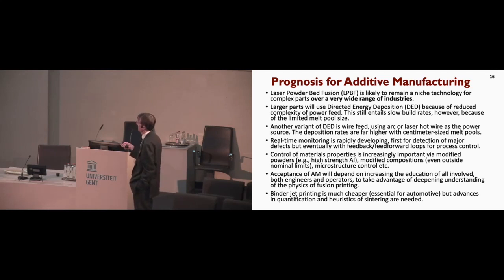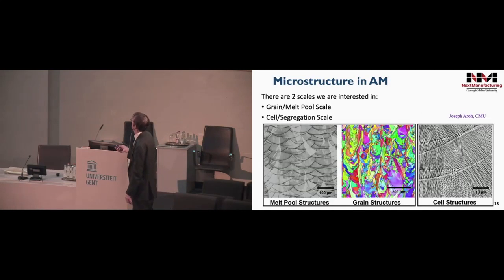And lastly, there's a variant called binder jet printing. It is much cheaper than any fusion technique. But the problem with it is you then have to sinter the powder. And sintering is another topic that's regarded as very mature: people have been doing this for decades and decades, why do we have to expend attention on it? But I can tell you, if you go and try to find a model for sintering that is a validated model, I think you will struggle for the most part. So that's a brief prognosis.